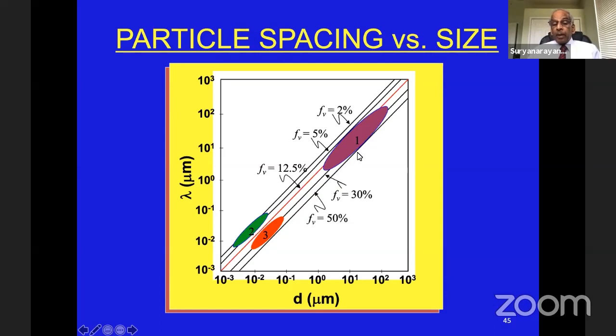This is easy. But if you go to very small size reinforcement, 10 to the power of minus 2 of a micrometer, that means about 10 nanometers, 100 nanometers, in that range, you can see that typically you can put only 2 to 5% of the reinforcement. More than that is difficult to mix thoroughly. But our goal is, can we increase it? Can we push this to this level, maybe 30% or 50%, like that?